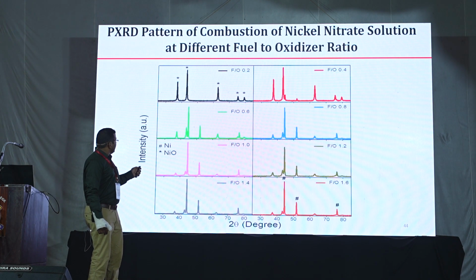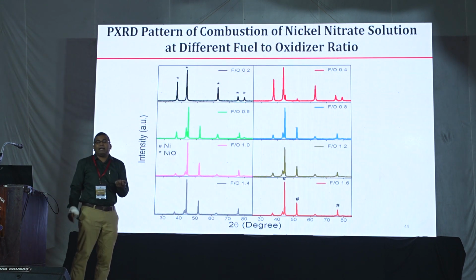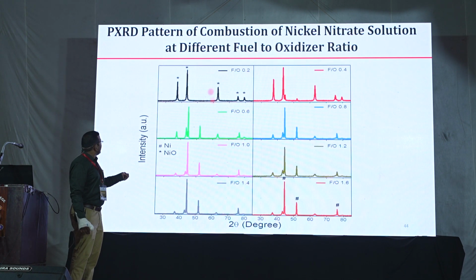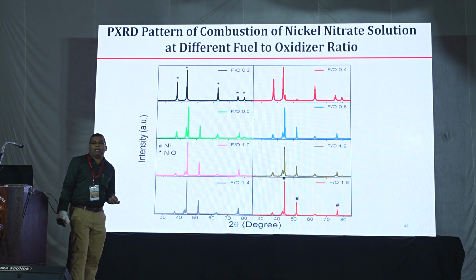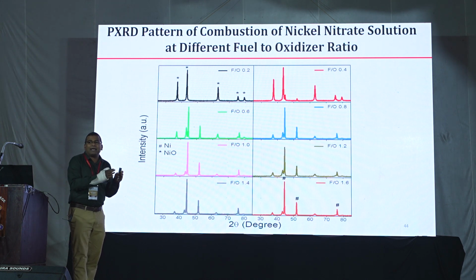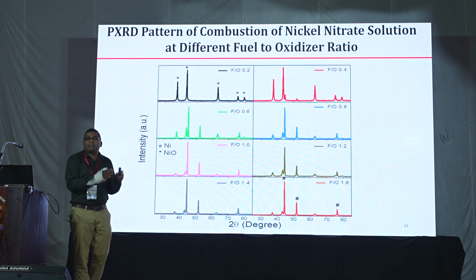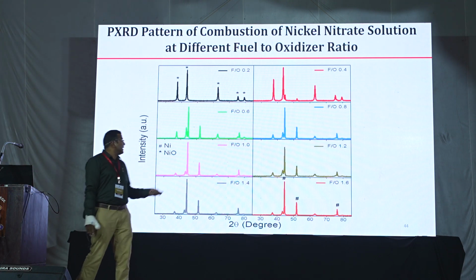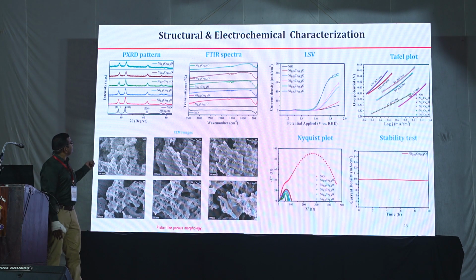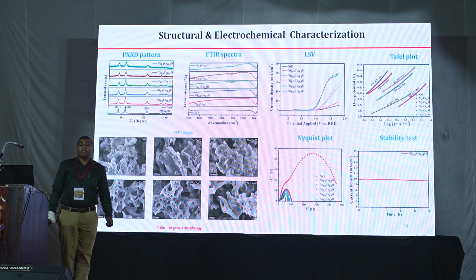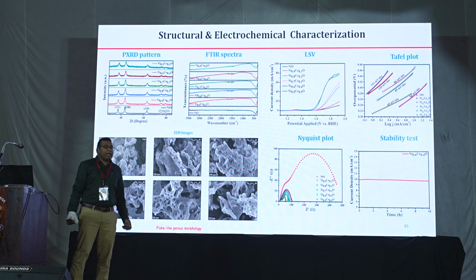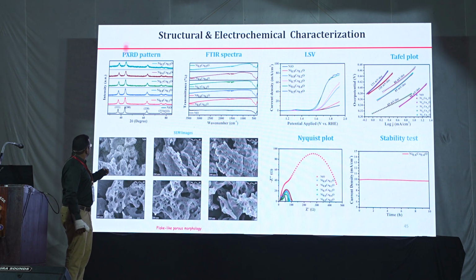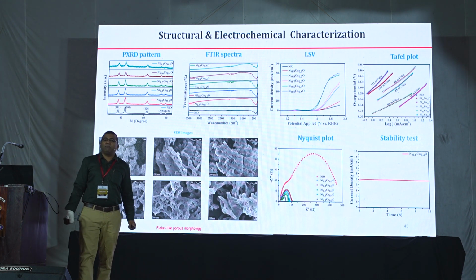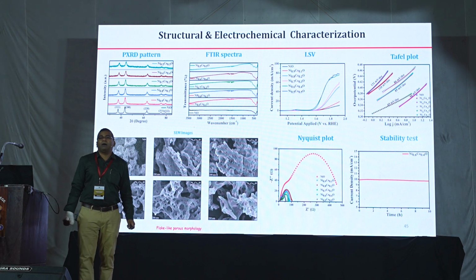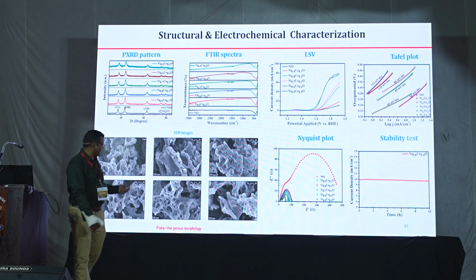Okay, suppose, this is one very simple example. If you start with nickel nitrate, you can have pure nickel oxide to even nickel. Okay, you can have a nickel oxide, nickel mixture, pure nickel oxide in different size, different morphology. All these can be tuned. Okay, so we did some substitution in the cubic nickel oxide. We made almost 50% substitution. But I can clearly say that no other method so far has reported substitution in the cubic nickel oxide actually.